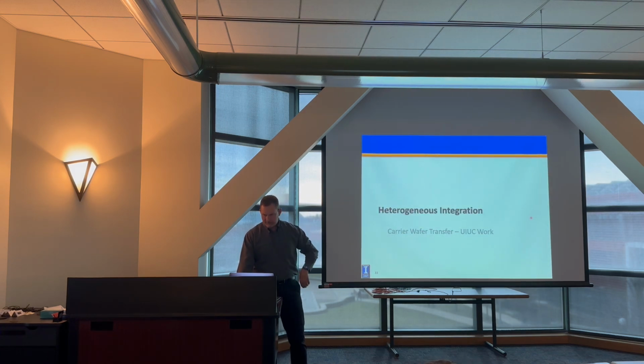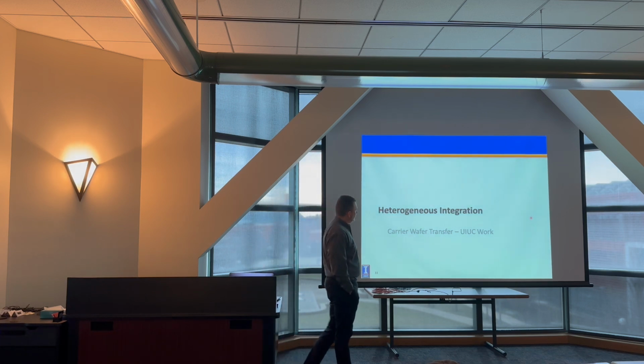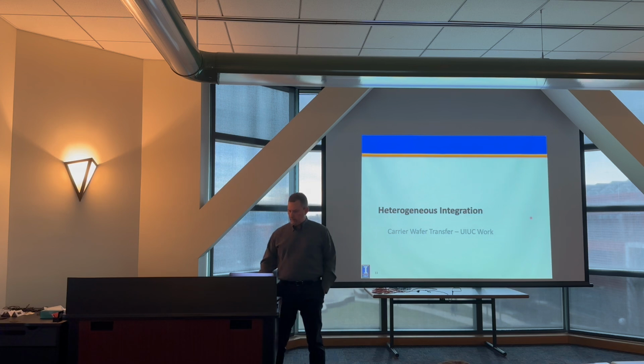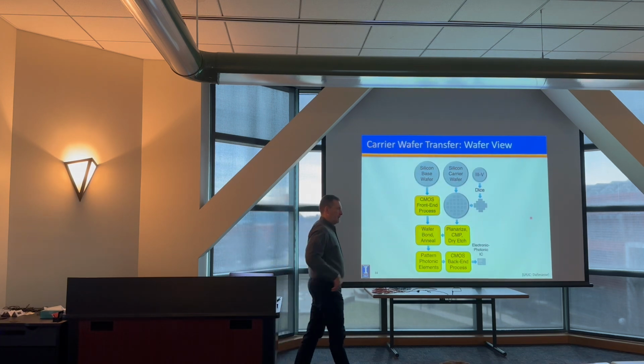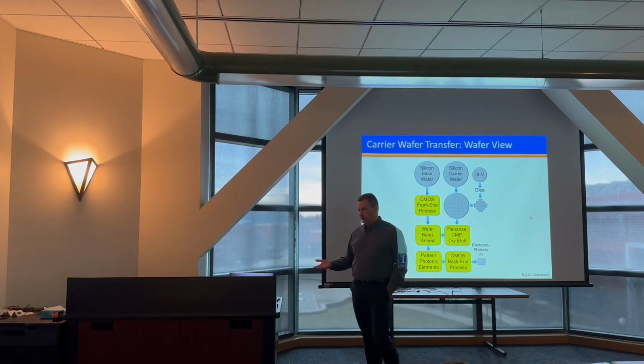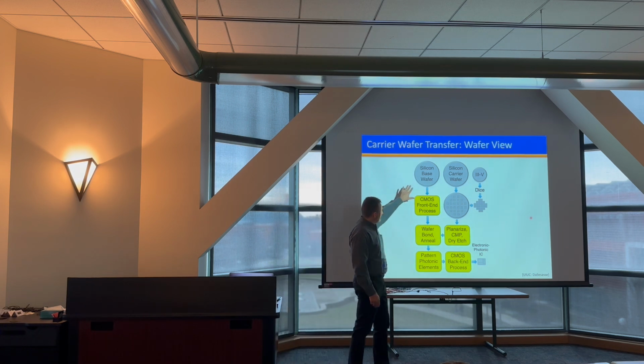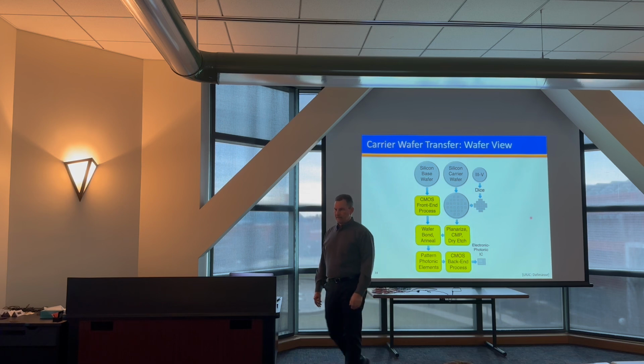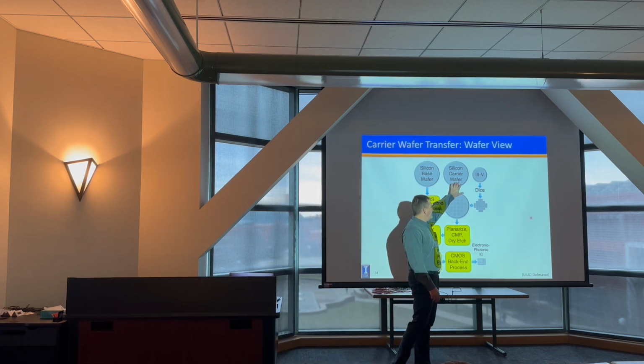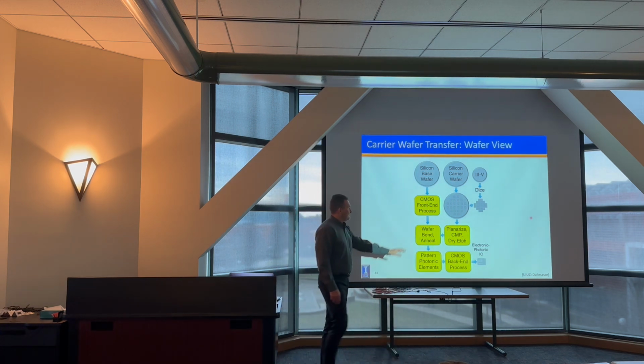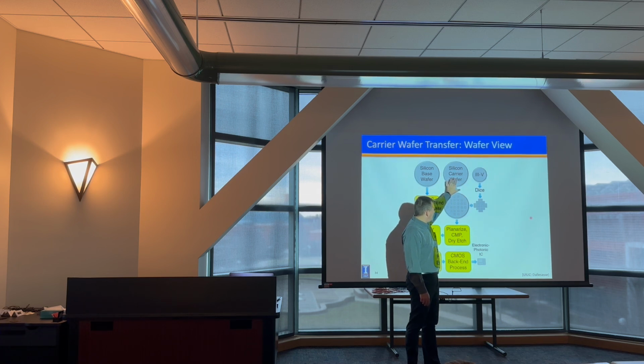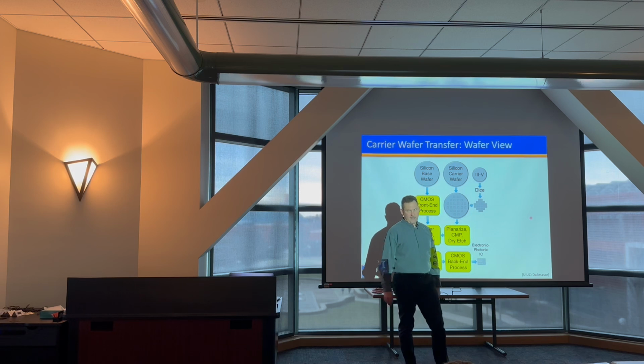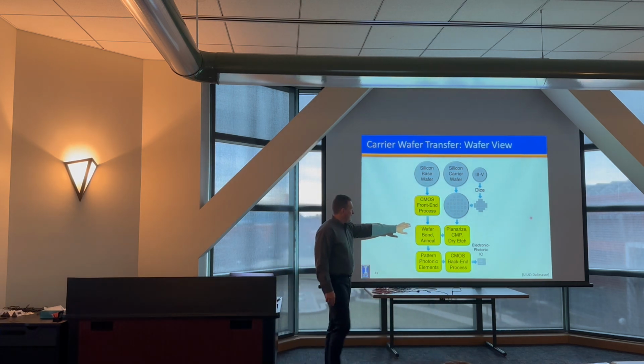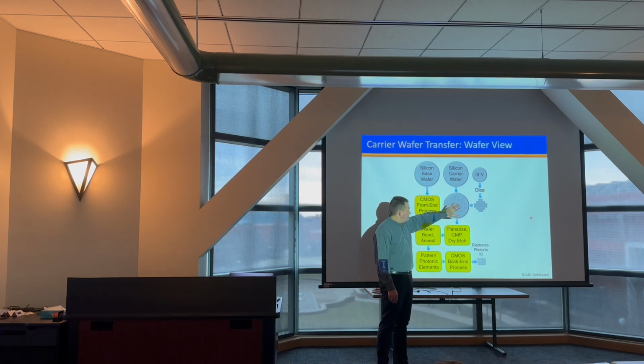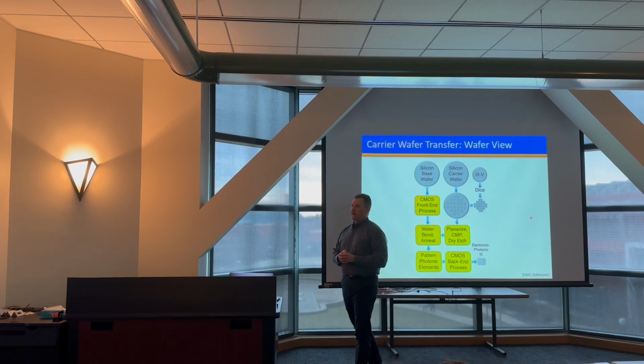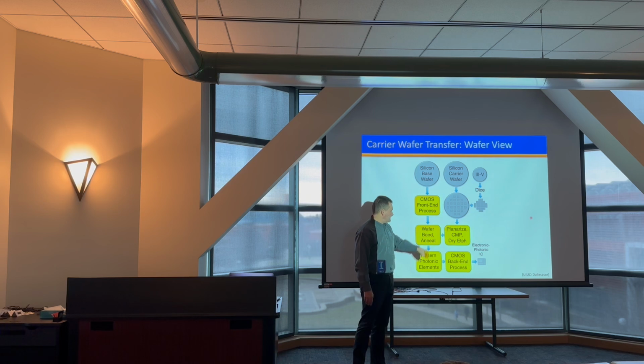People have also done things like smart cut with 3-5s as well. So, we're running out of time. I do want to talk about one thing that we're doing in Illinois, which solves the problem of wafer size mismatch without the variability associated with trying to use something like wafer tape to stretch your wafer. In this method, we imagine that we've got a silicon wafer going through the front end of line process of our silicon fab, and we have a second silicon carrier wafer, and then we've got our 3-5 wafer. We take that silicon carrier wafer, and after dicing our 3-5 material, we mount that epi side down on our silicon carrier wafer. We then remove our substrate, do photolithography so we can precisely define where those 3-5 islands are, and then do a single wafer bonding process where we bring these two together.